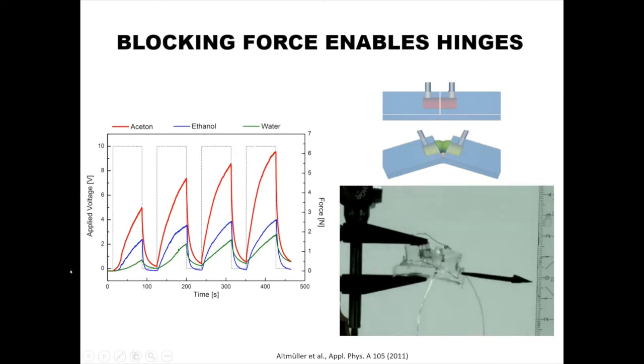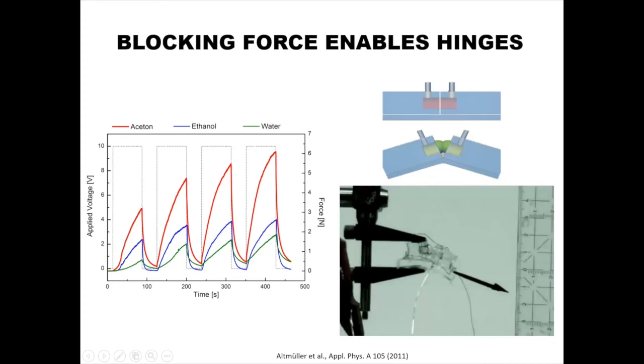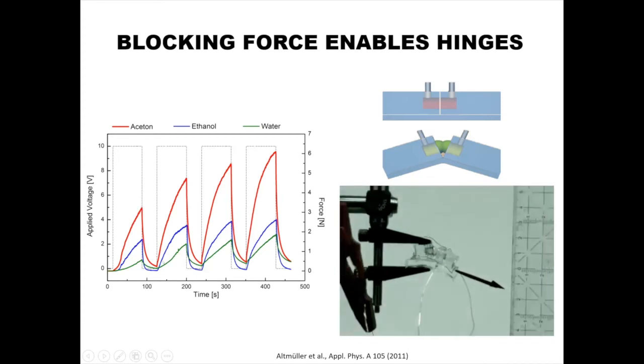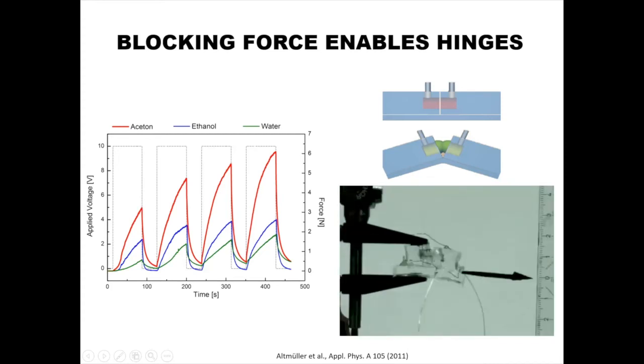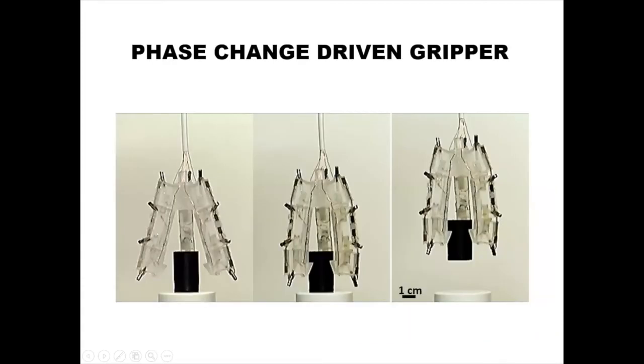So we also see a quite fast shrinking of our little bubble. And basically what we can create is a very simple antagonistic swelling and shrinking with our phase transition actuator. So we actually made hinges to make this little gripper where it can lift devices.